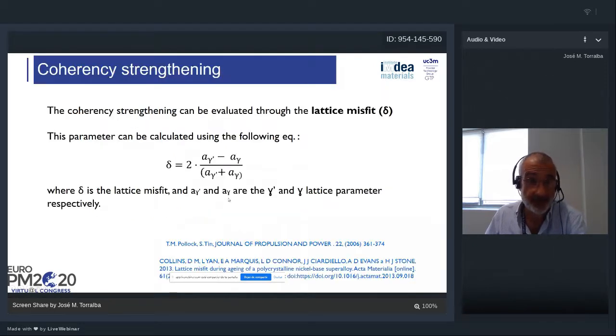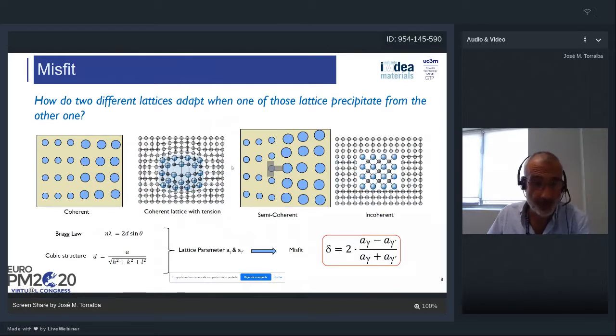What is the coherency strengthening? We can evaluate it through the so-called lattice misfit. The misfit can be calculated with this formula, in which we have here the lattice parameters of the gamma and the gamma prime, and we obtain this value that could be positive, negative, higher or lower, depending on these lattice parameters of the gamma and gamma prime phases. The coherency in some way increases the hardness or the mechanical properties due to the level of the coherency.